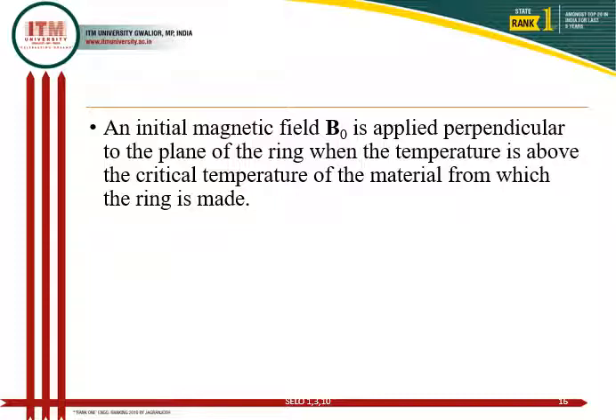If we apply a magnetic field perpendicular to the plane of the ring, and the temperature we keep above the critical temperature of the material from which the ring is made, then the magnetic flux phi through the ring will be B0A. And now if we cool the ring below the critical temperature, then the flux passing through it will not change.